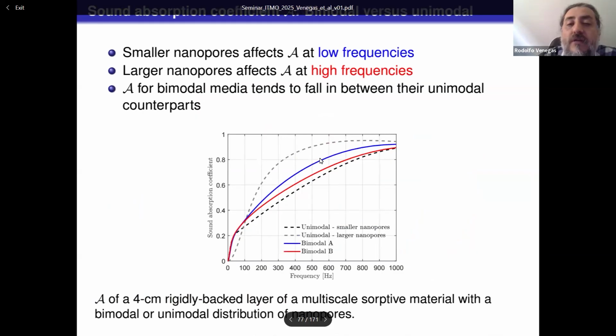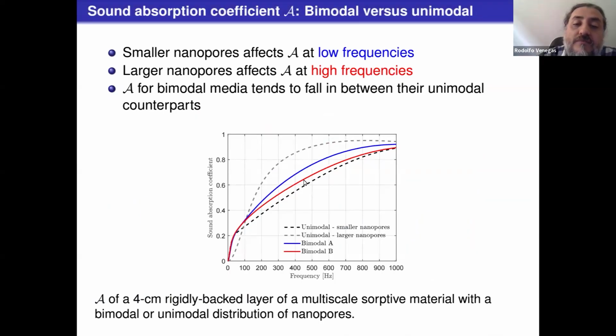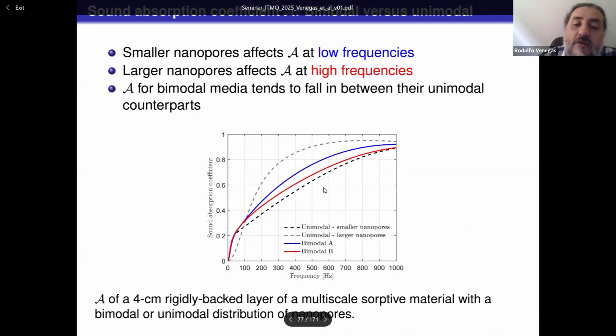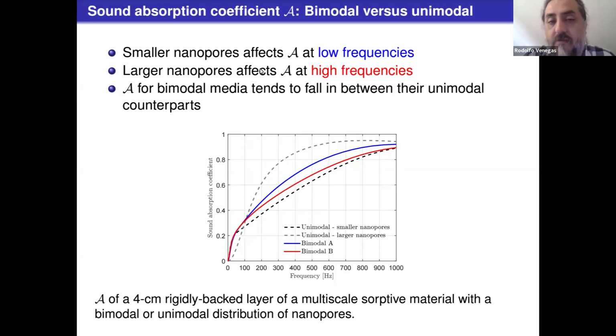So in blue, we have a bimodal nanopore size distribution, and B is another bimodal nanopore size distribution. And in black and gray, we have the respective materials with unimodal size distribution, with in particular the small nanopores in black and larger nanopores in gray. So we can see that the smaller nanopores are affecting low frequencies, while the larger nanopores are affecting higher frequencies, the sound absorption at higher frequencies, and the bimodal case is somewhere in between the unimodal ones. But here it's very close. So it is clear that the smaller nanopores are beneficial to improve sound absorption at low frequencies.